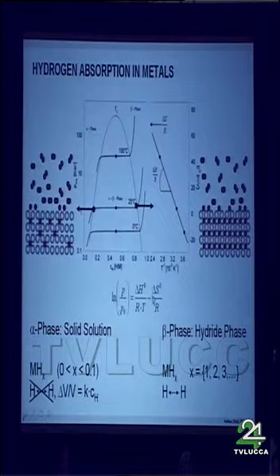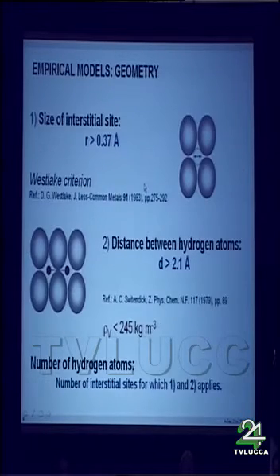From the Van 't Hoff equation, we can calculate, in a certain range, the pressure as a function of the temperature. And of course, for an application, it would be interesting to have the equilibrium pressure at the working temperature. But a storage system has to be laid out for the maximum possible temperature it can feel, and that means the pressure increases quite quickly if we increase the temperature, and especially the pressure increases very quickly if we are in the beta phase, in the hydride phase here, and dissolve some hydrogen in the hydride phase. This is a difficulty we have to overcome for an application.